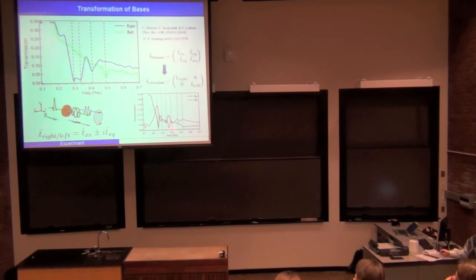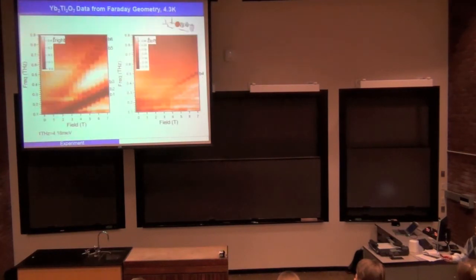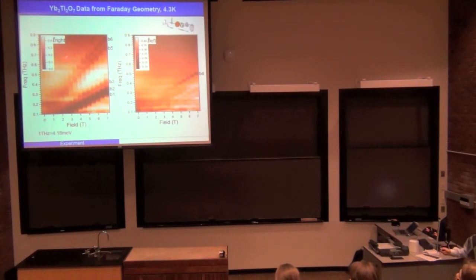So this is the same data set as this one, but now it's plotted in circular frame. So here I show the transmission in the right circular polarized channel and also the left circular polarized channel. And you can see right now the data is much easier to understand and much cleaner. So if we look at the data as a function of frequency and magnetic field at low temperature, we can generate these two plots. Here I show you the transmission in the right circular polarized channel and the left circular polarized channel here. The quantity being plotted is the transmission amplitude. So the brighter color means higher transmission, and the darker color means lower transmission. So wherever we have a dark line across the figure, there is a channel of magnetic absorption.